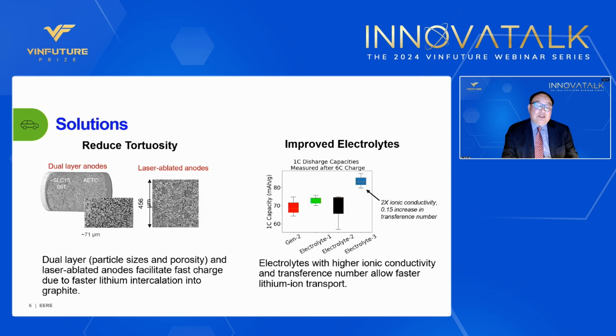with smaller particles inside and larger particles outside. By doing that, you facilitate much faster lithium intercalation into graphite. Another way to do it is a laser ablated anode. Basically, you burn the surface of the electrode and you can make holes in the electrode to increase the porosity. So that's one of the solutions. The second solution, you can see on the right-hand side, is to develop improved electrolyte with higher ionic conductivity and transfer number to allow faster lithium-ion transport.